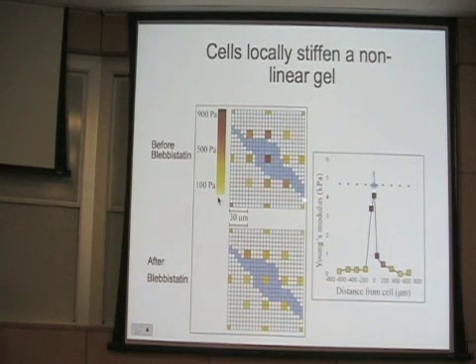When we began, if there wasn't a cell, the AFM would give us a very uniform stiffness of the fibrin gel that's about the same stiffness that we would measure in a rheometer. In this case, I guess a little less than 1,000 Pascal, a couple hundred Pascal. But if we look at the local stiffness near the cell, the stiffness near the cell is significantly bigger than the stiffness far away. And again, if we poison the contractile machinery, areas near the cell become soft again. They regain the elastic modulus of the bulk gel around it.